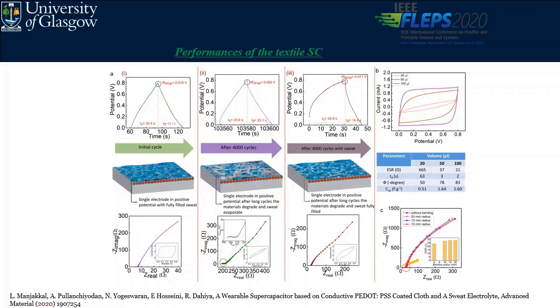But when increasing the number of cycles beyond 4000, you can see that the potential drop has increased. The reason behind this is that the material or the electrolyte got evaporated, because after 4000 cycles the sweat evaporated, and that significantly affects the electrochemical performance. You can see here that from 10 ohm it increased to 200 ohm.